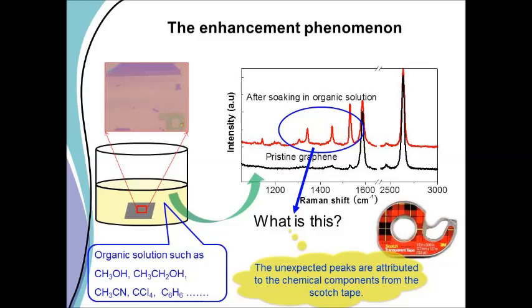Where do all these peaks come from when you have graphene? And why are they so big? Because the contaminants shouldn't be as big as graphene itself. So this is very interesting. So what's happening? This is the beginning of what we call the GERS effect. So surface-enhanced Raman, but this is graphene-enhanced Raman. If you have these same kind of molecules, instead of sitting with these particles, like in SERS, where they get big enhancement, they're sitting on graphene, you get a similar kind of effect. Not as much multiplication, only maybe a factor of 10 or 100.